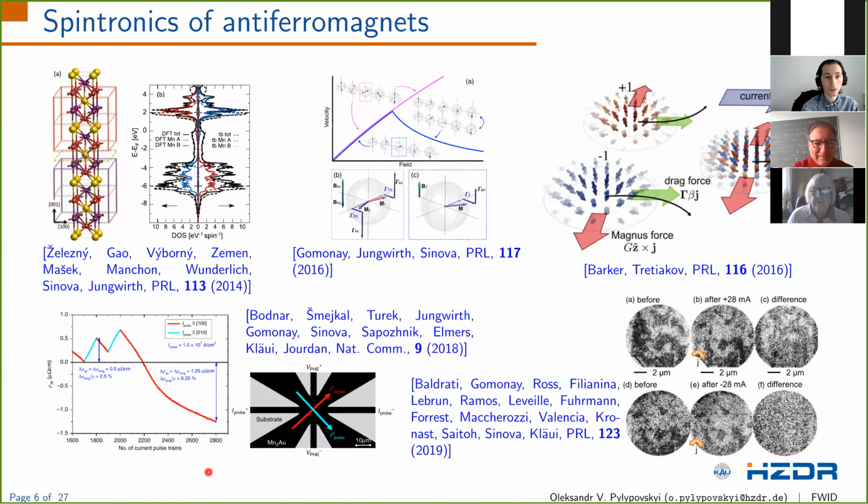The key obvious features of antiferromagnets include a strong robustness against external fields and negligible stray fields. For example, they promise much denser placement of antiferromagnet-based memory units. Of course, at the same time, this determines all the challenges in visualization and characterization of antiferromagnets. The last decade is marked by the rise of antiferromagnetic spintronics. Electric and spin currents show the possibility to switch the order parameter using current densities which are significantly lower in comparison with ferromagnets. One of the key enablers of the effective manipulation of antiferromagnetic textures are Néel spin-orbit torques. They arise in crystals with a locally broken inversion symmetry for magnetic ions.